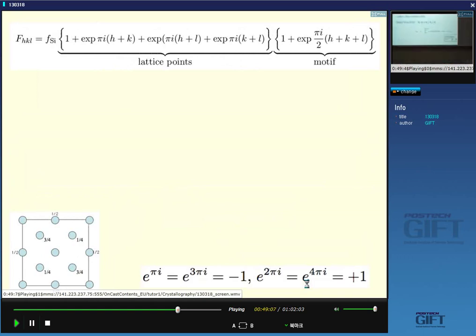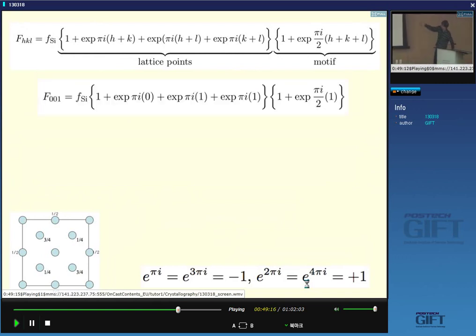Okay, so I'm now going to substitute numbers into this to see whether I get a 1, 0, 0 reflection. If I substitute for HKL as 1, 0, 0, then I get this expression here, this term, this term, and this term. And the motif is at 0, 0, 0 and a quarter, quarter, quarter. So I get an equation which looks like this. This is equal to 1, this is equal to 1, this is minus 1, and this is minus 1. So that means the intensity from the 100 plane will be nothing. We expected that because look, this is the 100 plane, and halfway we've got scattering centers which would scatter exactly half a wavelength out of phase.